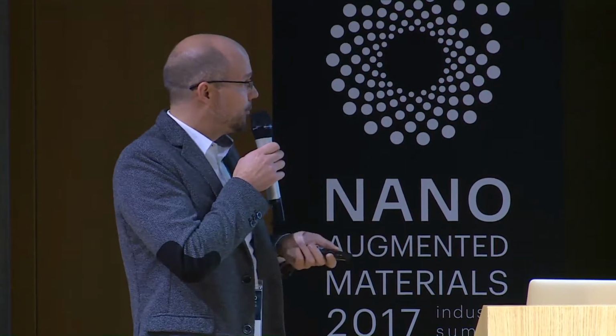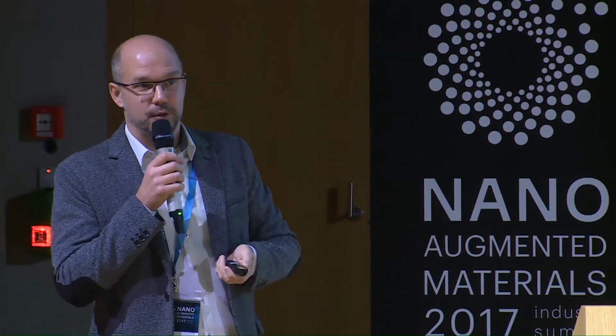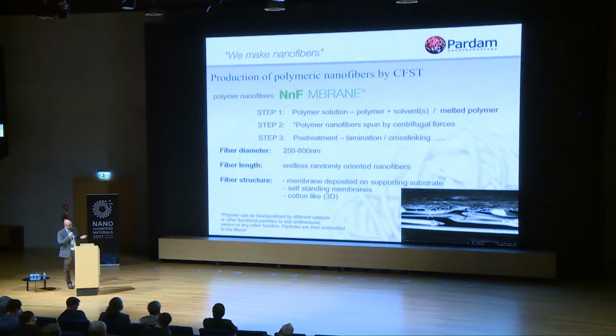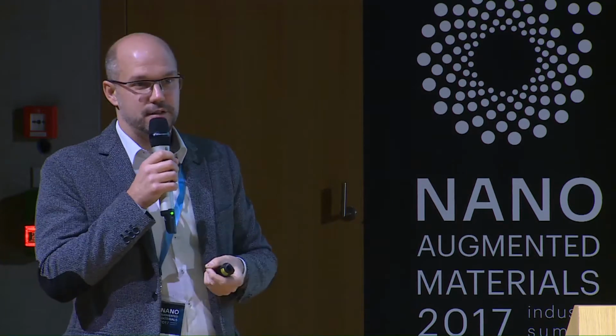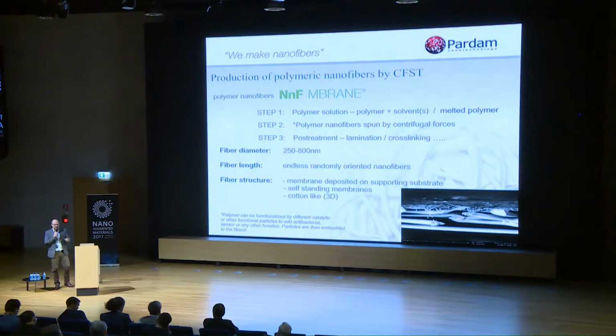Basically, to make membranes, you need a substrate which runs through the machine. You deposit fibers on the substrate, and very often, or for all of our products, we have to cover the nanofibers with an additional layer in order to protect them. Again, those polymers can be functionalized by different nanoparticles. We very often use silver nanoparticles to add antibacterial function for filters, for example. And we can add different substances into the fibers. So if we make filters, we can add, for example, vanilla essentials into the solution, and then the filters smell nice.